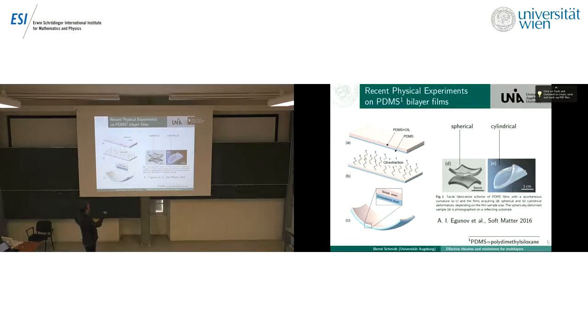So the first one is, if you have quite small, so you have still rather thick films, but the lateral extensions are somehow small, or to put it differently, the internal misfit between these layers is still rather small, then what you observe are these kind of parabolic or spherical caps. In contrast, if you have something which has larger dimensions which are much more extended, or if you have a much higher misfit in the material, then these things try to roll up.